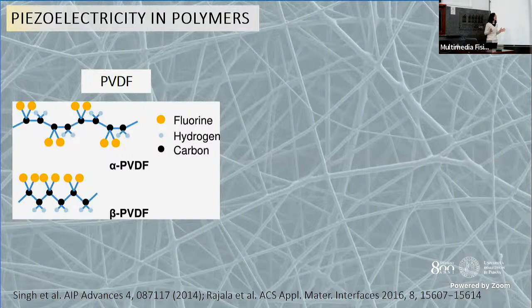The origin of piezoelectricity in these materials is still a subject of debate, because these materials are semi-crystalline, and the question is, does piezoelectricity belong to the crystalline part or to the amorphous part or something in the middle, so to the interface between crystalline and amorphous phase? There is not a clear answer to this question, but there is a lot of literature and a lot of clear evidence that if you increase one of the crystalline phases of the material, which is the beta phase of this material, you can increase the piezoelectric properties of the material.